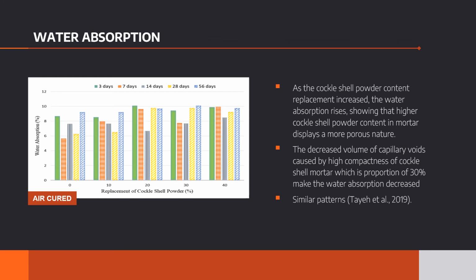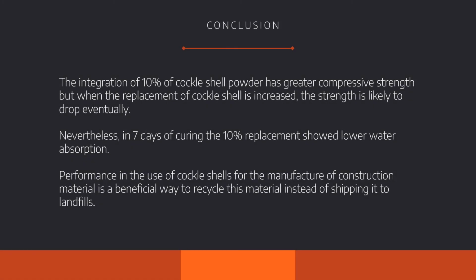The decreased volume of capillary voids caused by the high compactness of cockle shell mortar, at the proportion of 30%, makes the water absorption decrease. In a nutshell, the incorporation of 10% cockle shell powder has greater compressive strength, but when the replacement of cockle shell is increased, the strength is likely to drop eventually.